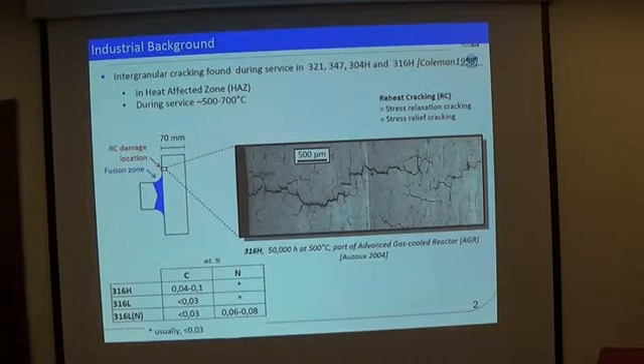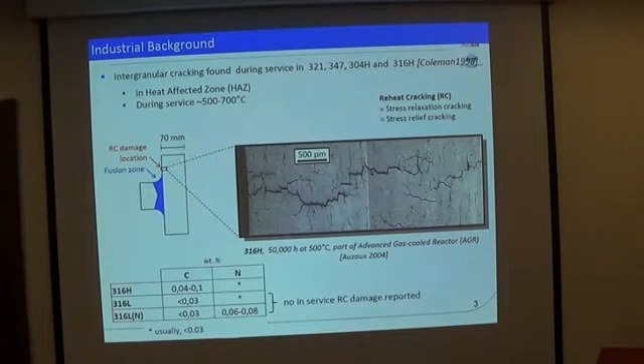There are several alloys here, stainless steels 316 that are employed, and for this one stress reheat cracking has been reported, whilst for those two, with lower carbon content, this has not been reported. So there is a difference in composition here, for these two alloys, lower carbon and more nitrogen.